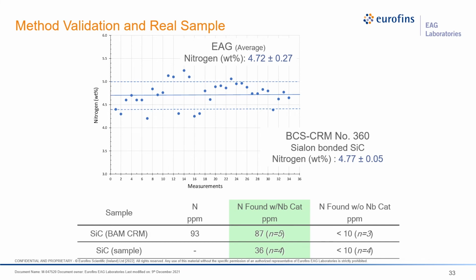In this plot, x-axis is showing number of measurements, while y-axis shows nitrogen weight percentage. As can be seen, our measurement for certified reference material number 360 yields a value of 4.72 plus or minus 0.27. Sorry, that is the value for our EAG average. The certified value is 4.77 plus or minus 0.05, which is close to the EAG average value.